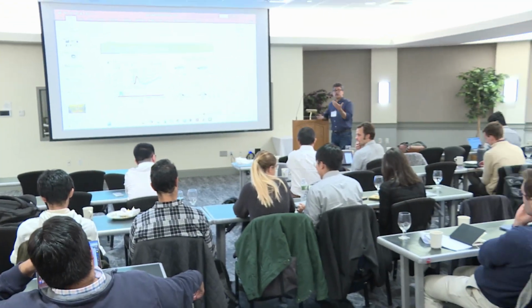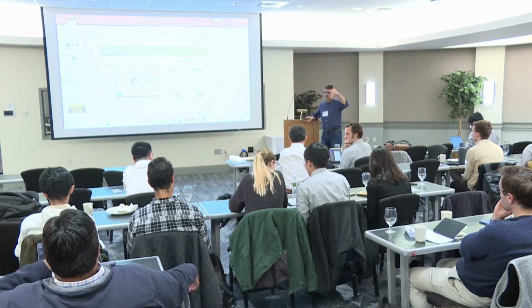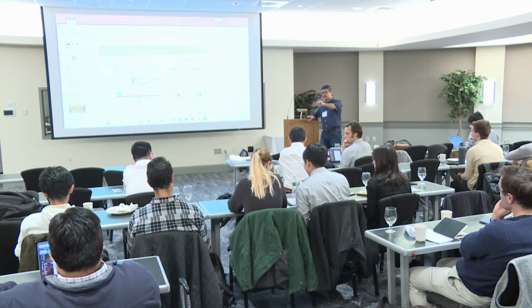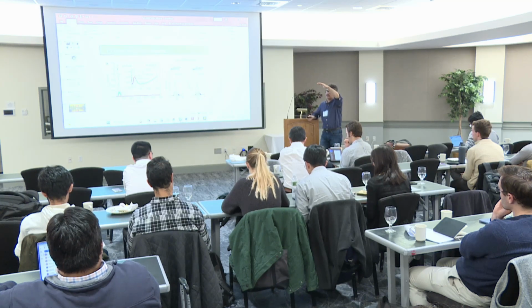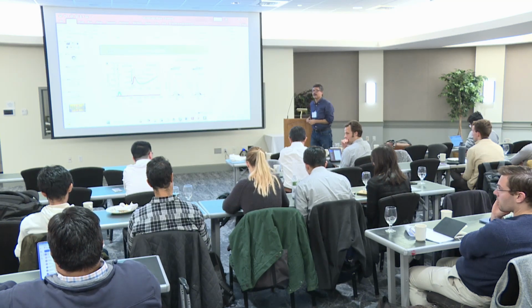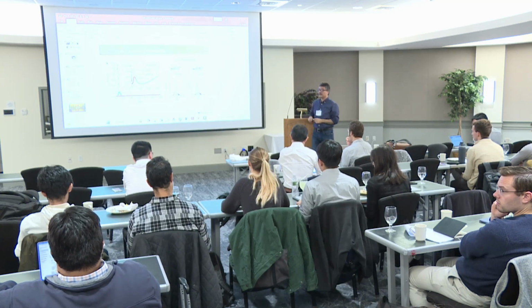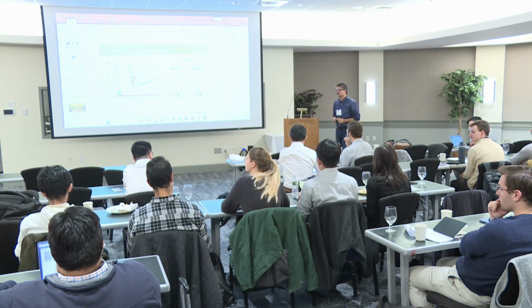I presume your europium is divalent. It is divalent, yes, you're right. We also looked at the X-ray absorption to see if there is any mixed valence, and we didn't find any. Also, when you measure magnetization as a function of field, the saturated magnetization goes exactly to 7 Bohr magneton, which corresponds to spin 7/2. This is a very relevant and important question.